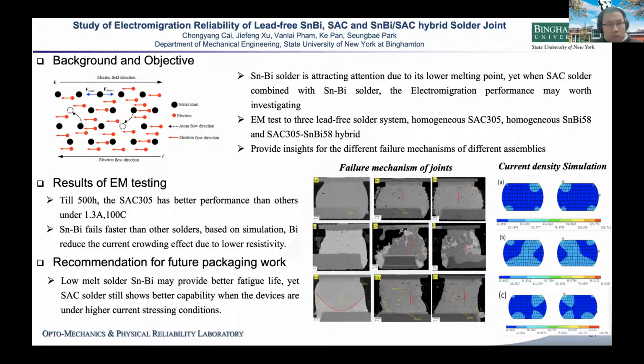Hi, everyone. My name is Chungyang, and the research topic I'm going to present today is the study of electromigration reliability of three types of solder joints: lead-free eutectic tin bismuth, SAC305, and hybrid solder joints of tin bismuth and SAC305. Right now, tin bismuth solder is attracting more attention because it has many unique advantages. The biggest advantage is a much lower melting point, which requires a much lower reflow peak temperature and reduces reflow cost. It also provides better thermal cycling performance. So we want to study electromigration to see if it also shows better performance than SAC305 when it comes to electromigration reliability.